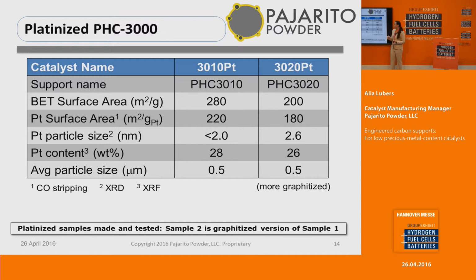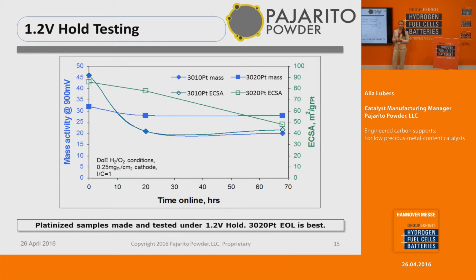Just in comparing our carbon surface area and our platinum surface area, overall, the less graphitic material, we see higher surface areas there. In comparing these 2 platinized materials in a 1.2 volt hold, we can see that our less graphitic material, the 3010, actually has a very high catalytic mass activity. However, over the length of the test, we see a drop in both mass activity and electrochemical surface area.